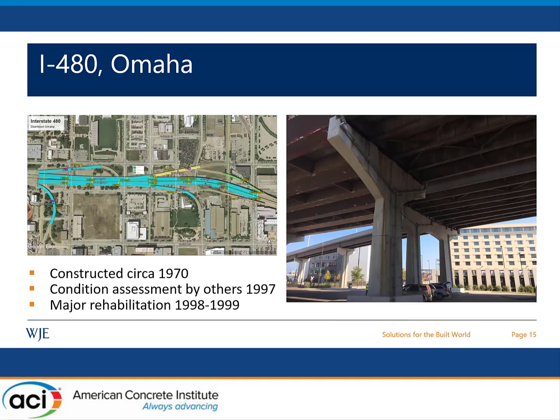And after about 30 years in service, there was a condition assessment performed by others on behalf of the Nebraska Department of Transportation in 1997 that looked at the condition of the bridge piers and made recommendations for their repair and maintenance. So this condition assessment included things like chloride sampling, delamination surveys, and crack surveys. And based on the findings, the party that performed that assessment recommended a series of rehabilitation activities between 1998 and 1999. And this included replacement of all of the joints and drainage systems on the entire length of the bridge section in this area, as well as surface repairs of 61 of the piers and electrochemical chloride extraction treatment, or ECE treatment, of 26 of the piers.